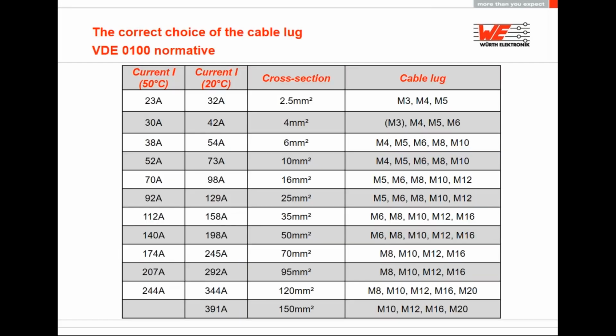And so we talked about the connector itself, but how do you choose the correct cable lug? So this table shows what current is specified for which diameter at a certain temperature, in this case either 20 or 50 degrees, and which size of cable lugs fits to those cross sections. So if you stick to this table and take care about the rating, there will be no problem with the current carrying capacity on the REDCUBE press fit technology.